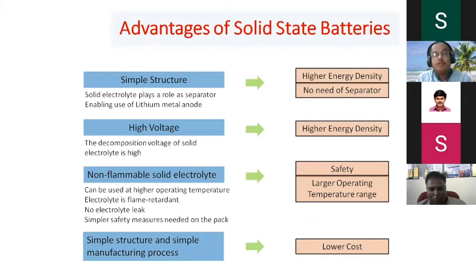If you ask me what the advantages of solid state batteries are: it's a simple structure, so I don't require a separator. The solid electrolyte itself plays the role of the separator. And if I'm able to develop a good solid electrolyte with good chemical stability against lithium metal, then I can think about enabling the use of lithium metal as an anode. Which means that since I'm able to use lithium metal, I could improve the energy density.